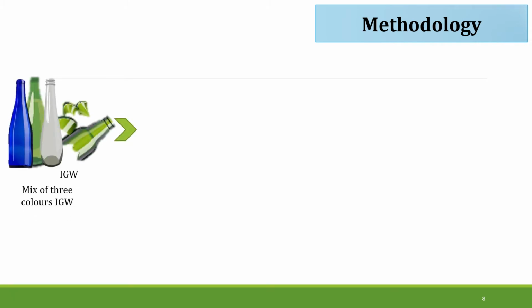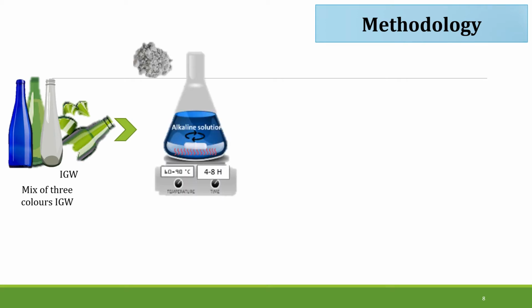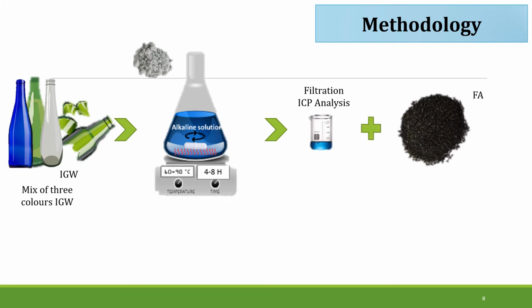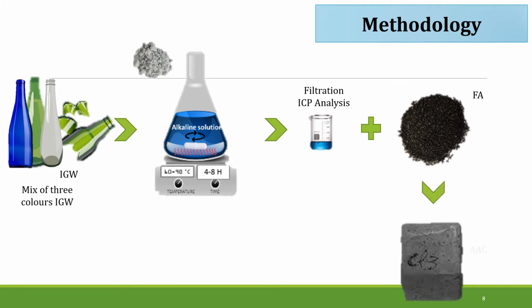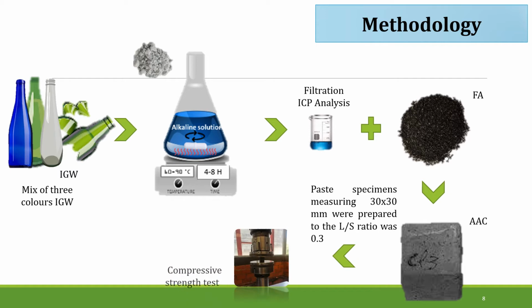In the second stage, a series of experiments are carried out with a reaction in which the glasses crushed at 38 and 75 microns are added to a 10 molar sodium hydroxide solution at different conditions ranging from 4 to 8 hours and from 60 to 90 degrees centigrade. Once the reaction is finished, the solution obtained is filtered and analyzed by ICP. Finally, with the solution that has obtained a greater amount of dissolved silicon, a mixture with fly ash is created to prepare a paste with a ratio of 0.3 and make an alkali-activated cement whose mechanical resistance will finally be measured by compression.